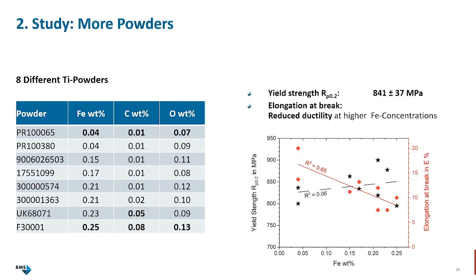It's difficult to say. So the influence of these material compositions on the mechanical properties was not that pronounced for the yield strength. So you see in black similar values for all and no clear tendencies. So with R square 0.06, there's no really linear fit. On the other hand, we saw that the elongation at break, which is a measure for ductility, was decreased with higher iron content. So here we have a clear tendency that higher iron makes the material less ductile.